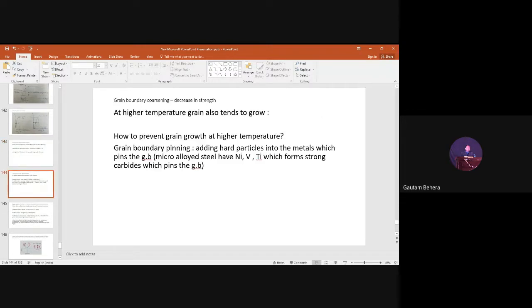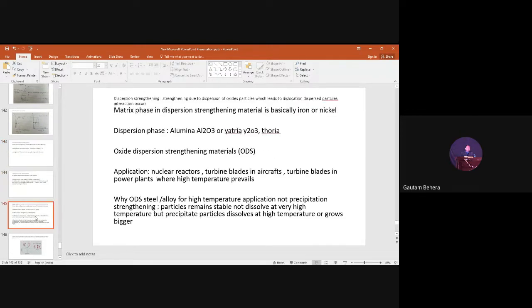Now, okay, just look at this figure. So dispersion strengthening is due to dispersion of oxide particles, which leads to dislocation-dispersed particle interaction. So the matrix phase in a dispersion strengthening material is basically iron and nickel. Anyways, the dispersion phase may be alumina, yttria, or thoria. These are called oxide dispersion strengthening materials, ODS. So we can have ODS steel also.